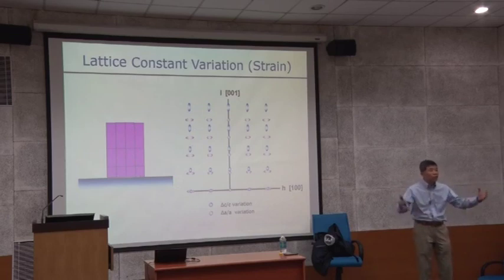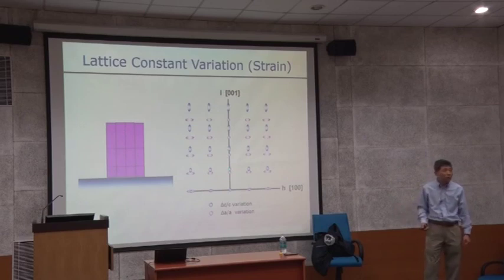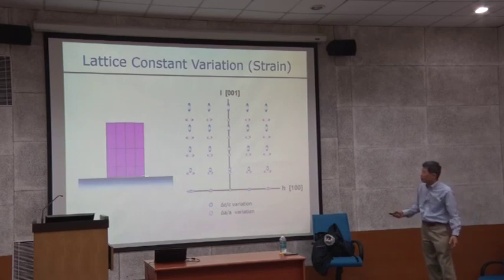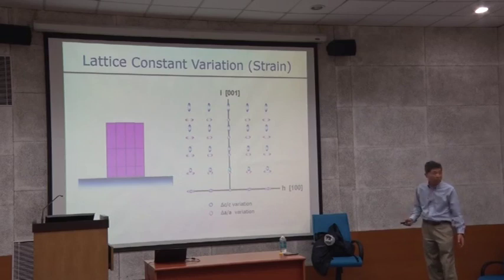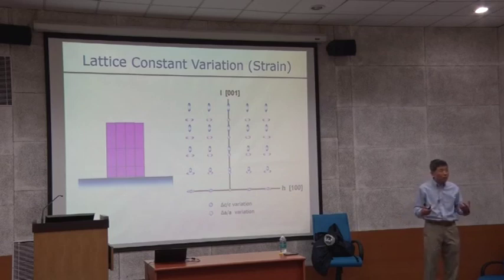Because the strain relaxation is different, for example. Okay? And then your strain relaxation is different, you get a different lattice parameter, then you get the elongation in that direction. Can you see that, the elongation? Because this one is shorter, short means the reciprocal space position is longer. So this part contributes to the bottom here. Can you see that? And this long one contributes to this position. That means this one contributed here, and this one contributed here. Do you get it, this one?